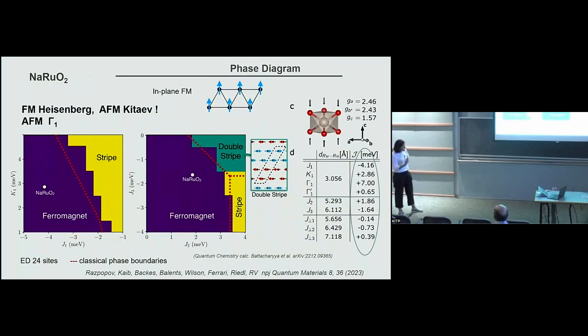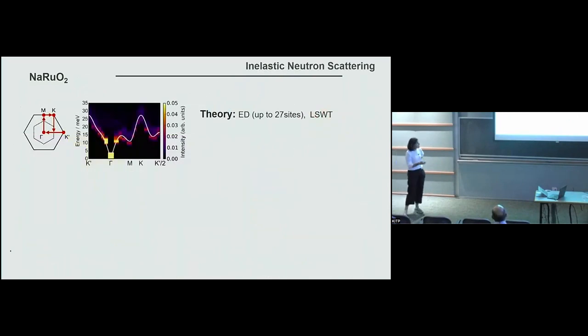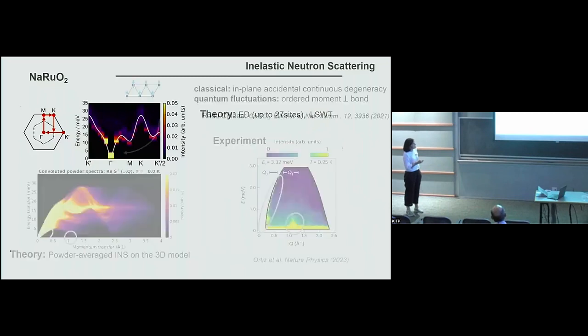So it's telling us that the system is very ferromagnetic. And even if we manipulate the interactions a little bit, the ferromagnetism is very robust. So can we explain the experiments with that? In fact, if you take these coupling terms,